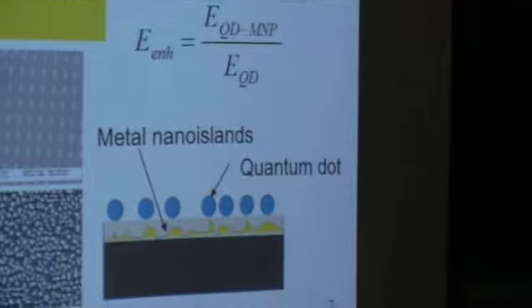So that's why the non-radiative decay cannot bring down the emission of the quantum dot as much as in this case. Here you have to remember that when you excite a quantum dot, the exciton that is generated, the electron-hole pair, can be grabbed by a defect and be gone, or it can end up as the radiation that you would like to get. So these two are always competing with each other. You cannot do much about the defects, but if you enhance the radiative decay, then you have more emission. And that's what's happening here, the reason for the enhancement of emission.